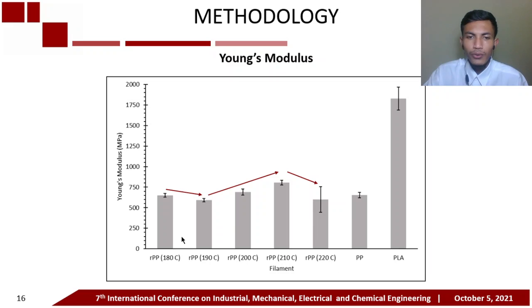The drop in value at 190 Celsius was thought to be due to the presence of voids, affecting the interior of the dog bone samples. The presence of voids plays a major role in reducing the density of the samples. The more voids, the lower the sample strength.